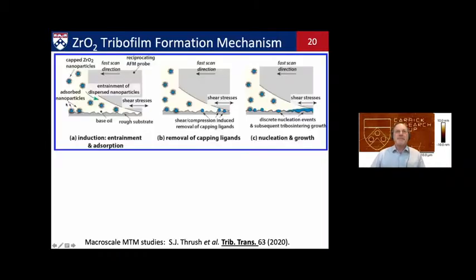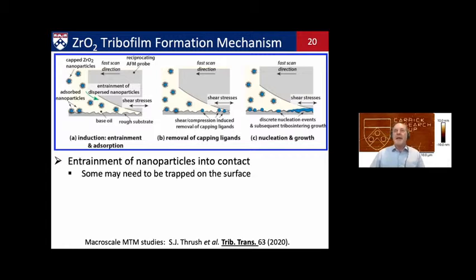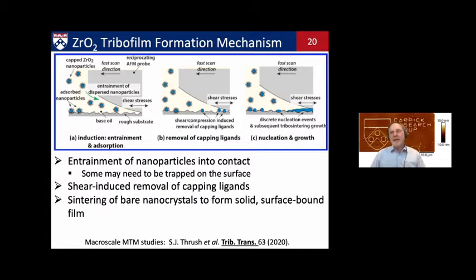So what we think is happening is that nanoparticles are adsorbing and being entrained into the contact. Through a process we're still working to understand, those capping agents are somehow removed, and the nanoparticles fuse together. It's almost like sintering of ceramic particles, assisted, we think, by the stresses that we're applying. So entrainment into the contact, shear-induced removal of the capping ligands, and then sintering of those bare nanoparticles to form films. And we even see in the TEM some coarsening or grain growth of the zirconia. There's a nice paper just this year from Steve Thrush and Alan Comfort at CCDC in the Army Research Lab, looking at this at the macro scale.